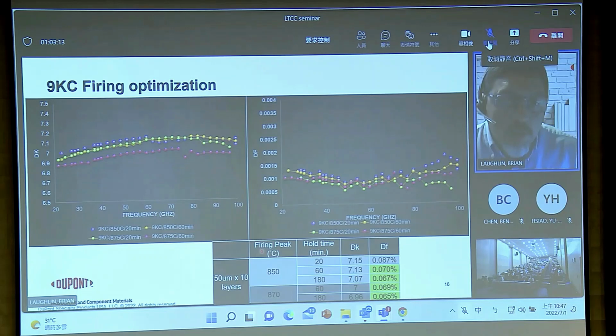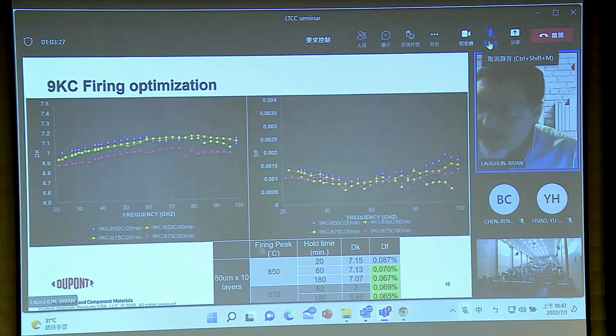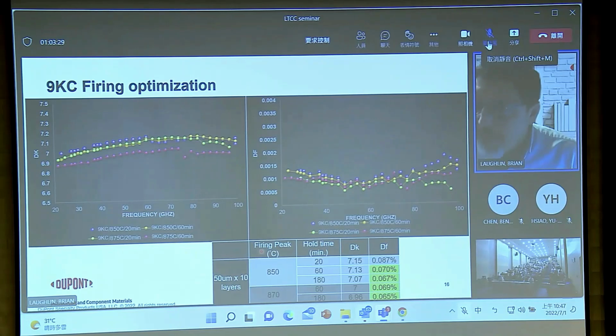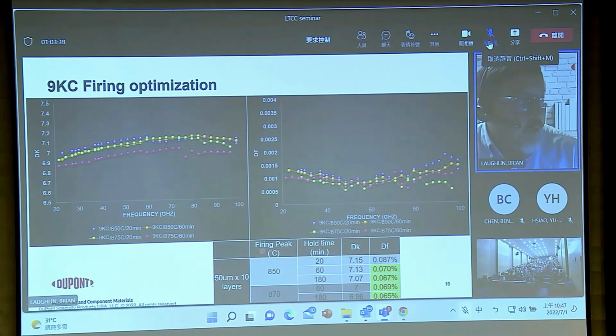I would say you have this latitude to try and tune the process and balance the economics of your process versus the performance you want. But if you have process latitude and process variation on the scale of you don't hit 20 minutes exactly, it goes to 18 and a half, 21 minutes, or you're not at 850 exactly all the way through the whole zone of your furnace, you might be 10 degrees, 5 degrees off here or there, you're not going to see huge process variation shifts. And so you should keep really good yield because it's pretty stable in repeatability.